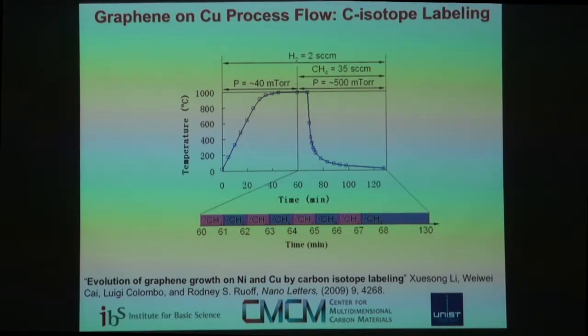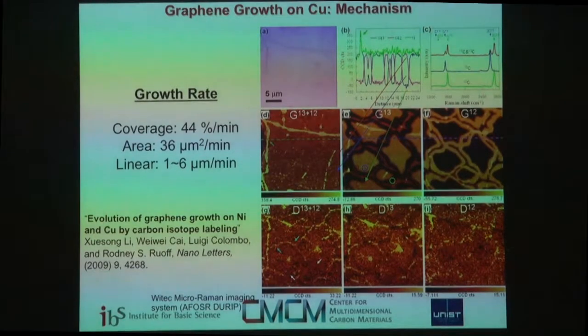If you use nickel, where the concentration is 1 atomic percent at 1,000 degrees C, then when you cool, if you have a thick foil and you've exposed for a long enough period of time that it's almost saturated, you get graphite on the surface, not graphene. But to really nail it down, we then took this approach of using C13 labeled methane and then normal methane during our so-called growth or exposure to methane. And on copper, we got an entirely different result than we did on nickel. And it's exemplified by these micro-Raman mapping images.